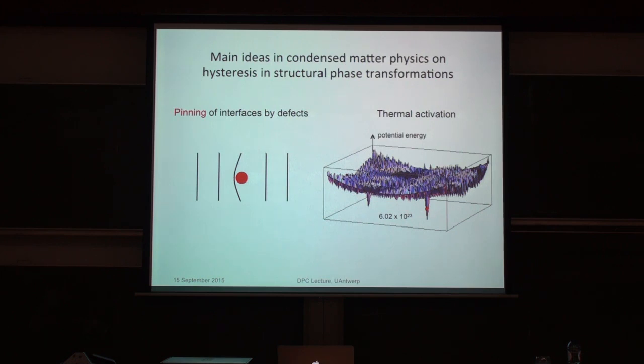And if you raise the temperature, you increase the thermal motion, and this point goes over here, and maybe at the higher temperature, it finds its way out of that deep well, and that's the phase transformation, and it sits out here. In fact, people believe that the average position of that dot is maybe not even in a well, maybe even in a local maximum. And the concept of that is that the austenite would be stabilized by entropic effects.